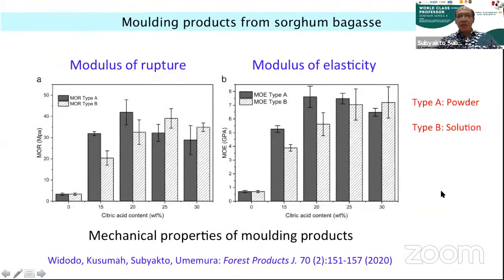This is the result. If we compare the powder type and solution type, the powder type is a bit better compared to the solution type. And if we consider the citric acid content, we can see here that 20% citric acid gets the highest properties, also in the modulus of elasticity.